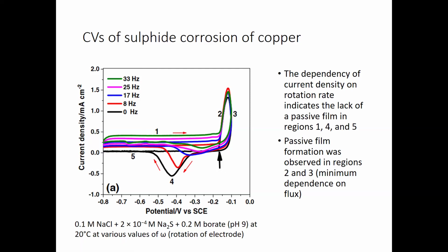So if you remember before, there's kind of 2 limiting factors when it comes to corrosion. You can either have a mass transport limitation, or you can have a charge transport limitation. One of the important aspects when it comes to passive coatings is that you're expecting there to be a charge transport limitation. That passive coating is going to degrade further corrosion enough that the only thing controlling corrosion should be charge transfer. But instead what we see is an effect of mass transport.